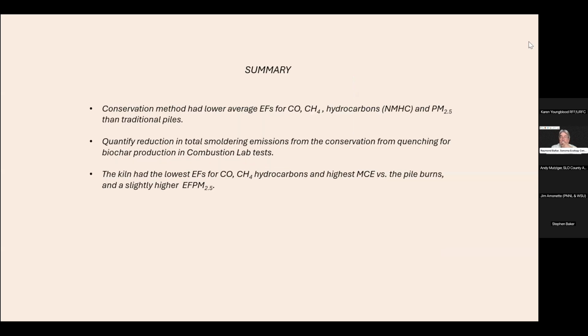So in summary, the conservation method had lower emission factors for CO, methane, hydrocarbons, NMHC, and PM 2.5 than the pile burns. And for the lab burns, I wanted to quantify the smoldering emissions that were produced after the quenching time, because I think that's where really the advantage in terms of emissions for the conservation burns is, not the actual emissions between the two during the burning phase, but actually what you save in terms of emissions coming later. And the kilns had the lowest emission factors for most of the species that we measured versus the pile burns.